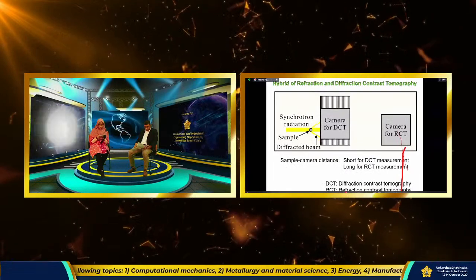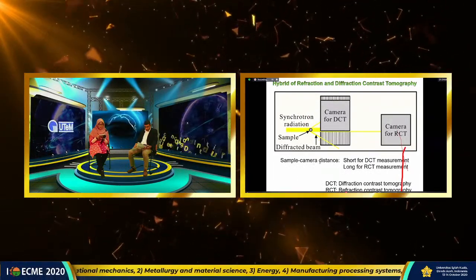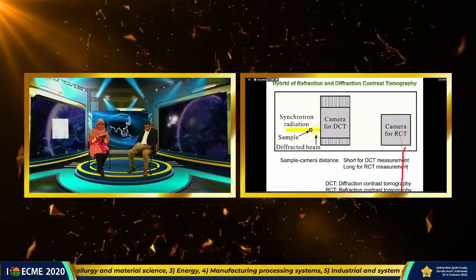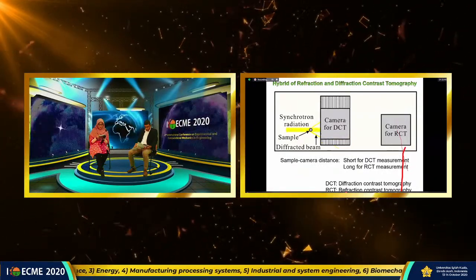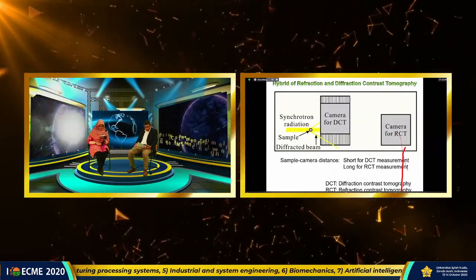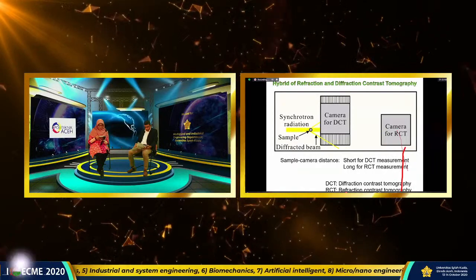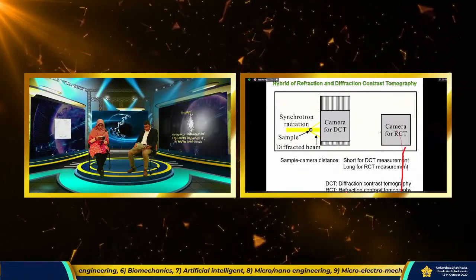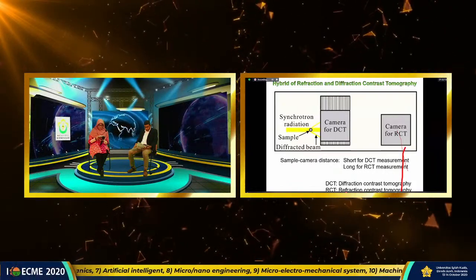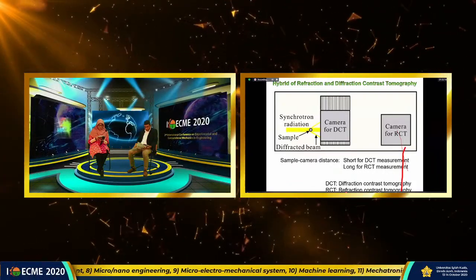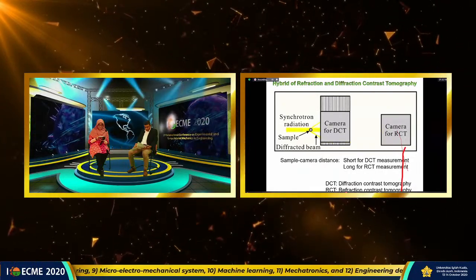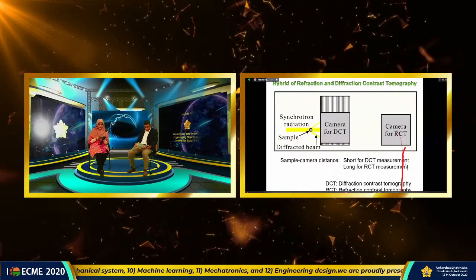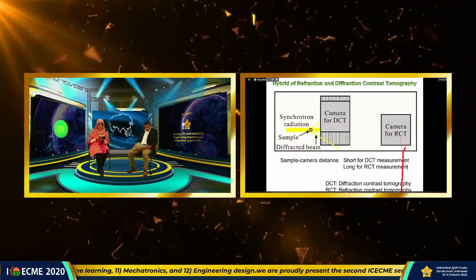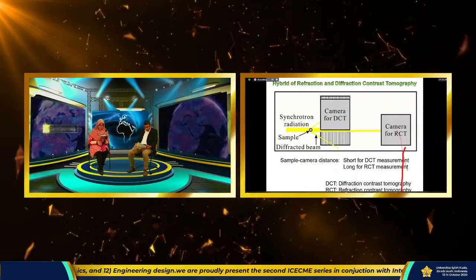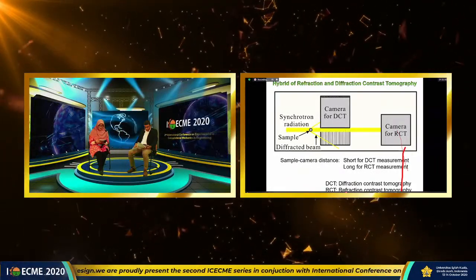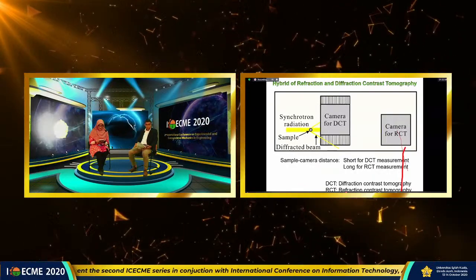For diffraction contrast tomography, the distance between the sample and detector should be short enough to detect as many diffraction spots as possible. On the other hand, the distance should be long enough to obtain a large effect of refraction contrast. We developed a dual camera system like this. This camera can move to avoid blocking the X-ray beam for refraction contrast imaging. Using this system, you can observe a crack and misorientation of grains almost at the same time.